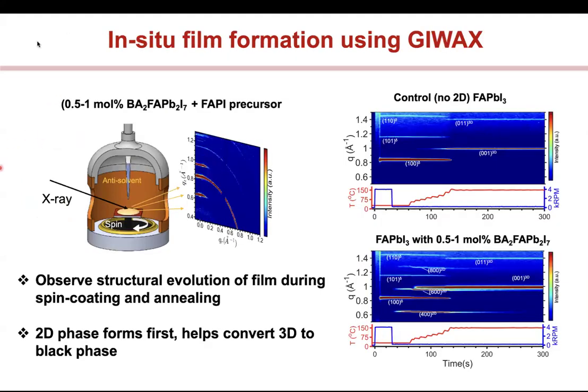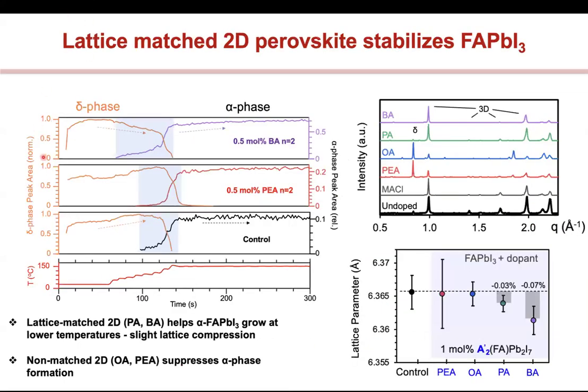And so now, in order to do this in a real film, making it a scalable process, what we did was we used this 2D perovskite, very small amount, 0.5 to 1 mole percent, and added this into the FAPI precursor and performed these in situ measurements. These are basically you spin coat and you're looking at X-ray diffraction signatures. And we did this for controls and for this. And in fact, what we found was that indeed, you get this very nice conversion, and I won't go into details of this just to save some time for questions.